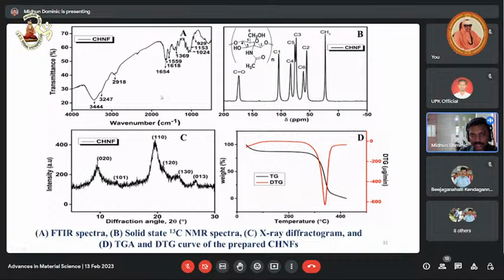There are two peaks at 1654 and 1618 centimeter inverse that show alpha chitin is present in our sample. C13 NMR also shows alpha chitin is present in the sample. XRD also affirms the formation of alpha chitin, and the crystallinity index can be calculated from the X-ray data. The crystallinity index of chitin nanofiber is around 90%.